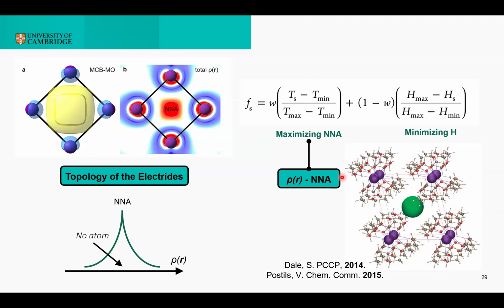So the electron density at the non-nuclear attractor now is maximized. So we want systems that have a lot of electron density in these non-nuclear attractors, where the enthalpy is minimized in this case, as previously. So we want stable structures. If no non-nuclear attractor was found, basically this objective was set to 0, so it was not an electride.